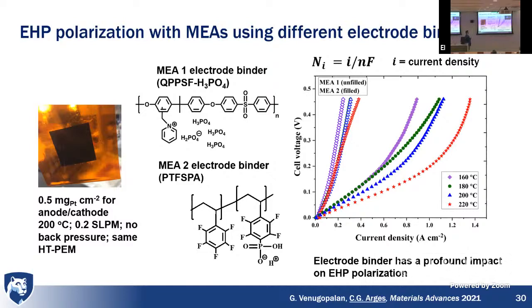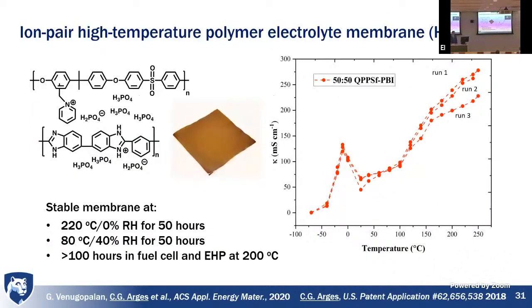So this MEA1, these are the open data points for different temperatures. And if we try to get high current, that's the rate at which we're purifying hydrogen at the pump. As I try to get the current higher, move more hydrogen through the pump, my voltage skyrockets, right? I'm using all this energy and I'm not getting any more hydrogen purification. But if I change that adhesive to a different material, hey, I'm getting a lot more current now at lower voltages. And why is that the case? This binder has a really big impact on hydrogen pump polarization.